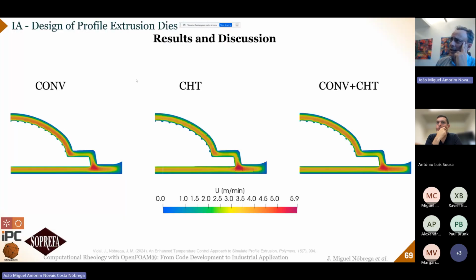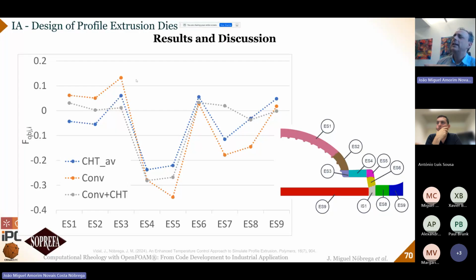In this case, there is a significant difference in terms of pressure drop by using the more accurate measurements. In terms of the law distribution, we see also some features, and in terms of the objective function, there are even different signs. So depending on the approach we use, we might be on the opposite side of the correction. So we could be misled to perform corrections that are not required in the tool.